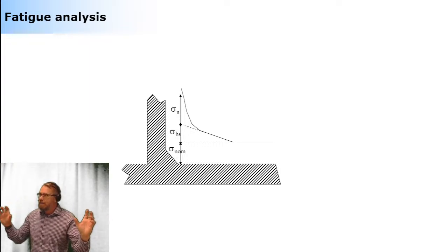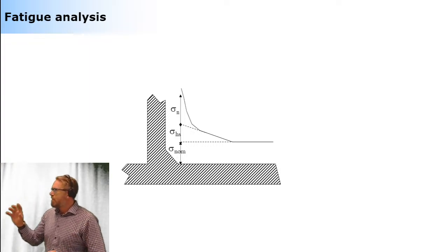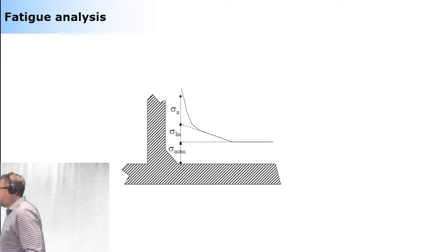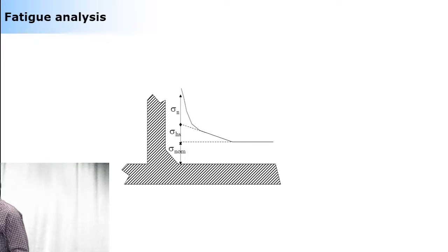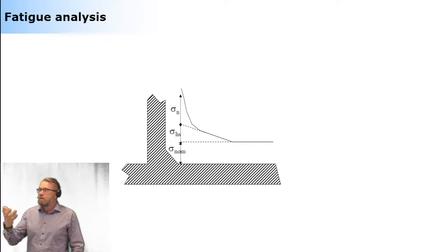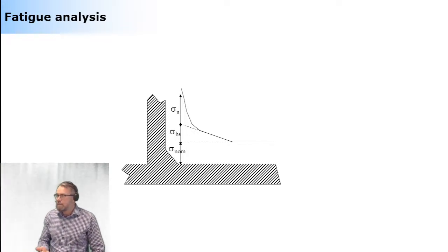But now, again, if you take a close look, if you make a finite element model of this kind of structural detail, and you make your finite element mesh very fine close to where the weld toe is located, you will see that the stresses actually become very, very high. They will actually go almost to infinite numbers. And this is simply because of the geometrical singularity you can see here.